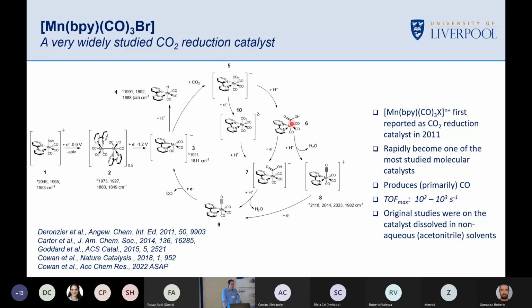You might think that increasing the proton concentration is then detrimental to the CO2 reduction efficiency. This catalyst is a little bit unusual, but it won't actually bind CO2 unless there's a strong enough acid source present. And as you increase the acid strength, you actually push the system away from protonation towards CO2 binding. So it's kind of, to us, initially counterintuitive, but really, much smarter people who do theoretical chemistry explain this and why this happens.